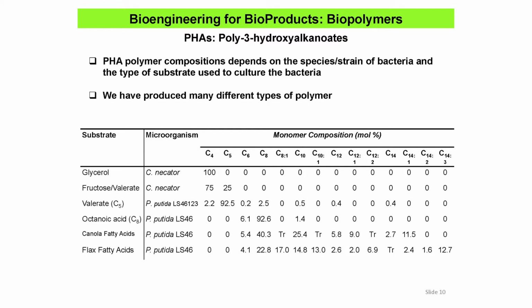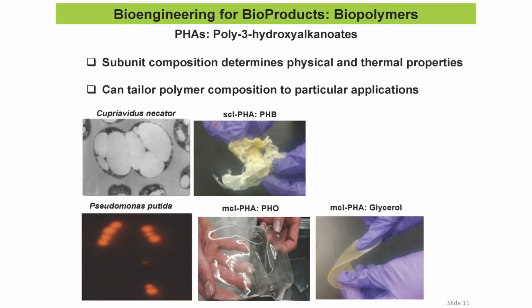And if we then use medium chain or long chain fatty acids from oils, for example, we get more and more side chains with different carbon chain length, and we even get unsaturated side chains with 1 or 2 or 3 carbon-carbon double bonds, which is very interesting because then you can play with the chemistry and you can oxidize them so they cross-link to other things, which I'll come to in a minute. So basically the subunit composition determines the physical and thermal properties, and we can tailor the polymer composition to particular applications. So this is polyhydroxybutyrate, a polymer that's 100% 4-carbon subunit. It's very crunchy and very brittle, but it can be extruded into threads, which is what they use in the sutures. You can make bottles out of it, but they tend to break if you drop them on the ground.